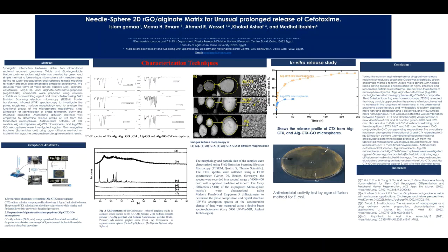The membrane diffusion method was employed to determine the release profile of cefotaxime from the fabricated microspheres. Antibacterial activities of cefotaxime solution, alginate microspheres, alginate cefotaxime microspheres, and alginate cefotaxime graphene oxide microspheres were investigated against the gram-negative bacteria Escherichia coli using the agar diffusion method on Mueller Hinton agar. The prepared samples gave excellent results.